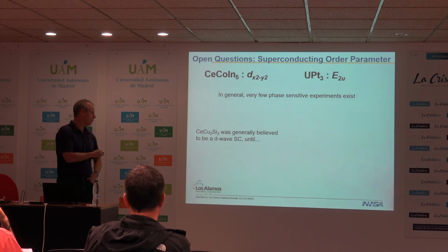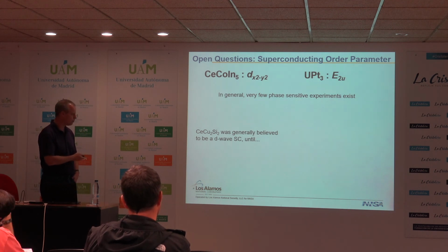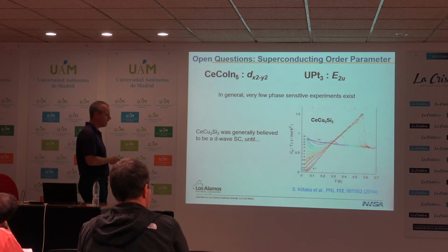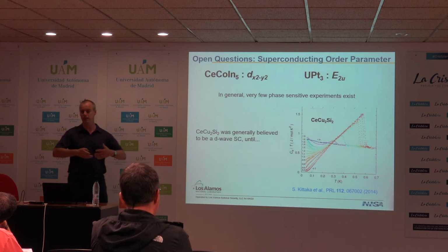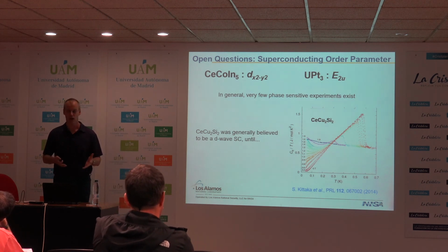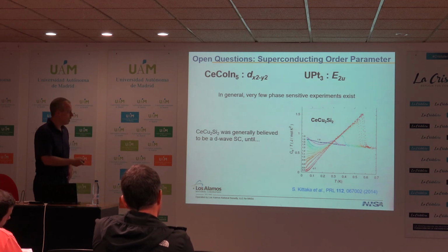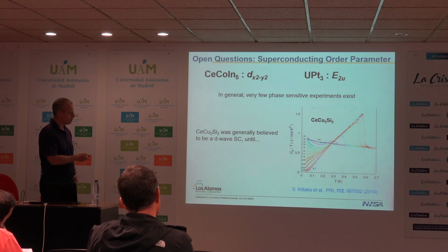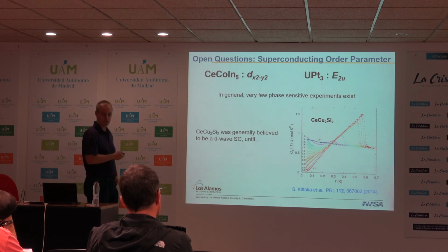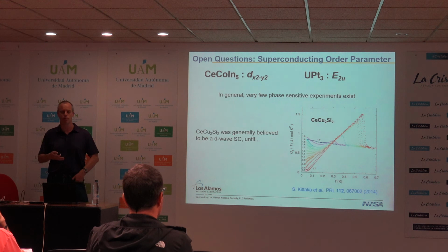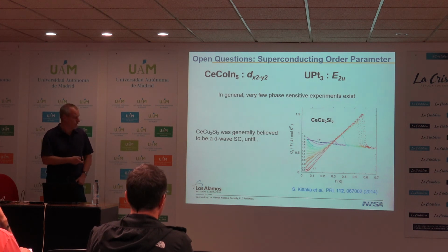And it really is an issue because we take the example of cerium copper 2 silicon 2, and we heard earlier that it is now believed not to be a D-wave superconductor. So cerium copper 2 silicon 2 is tetragonal. It looks a little bit like cuprates, and for a long time it was thought it must be a D-wave superconductor, but then low temperature specific heat measurements done in Japan really showed that at the lowest temperatures you're rolling over into what looks like a fully gapped scenario. So this can't be just a simple dx squared minus y squared. It's still believed to be unconventional, but how to reconcile these measurements with the order parameter, with neutron scattering, which sees the spin resonance, is an open question.